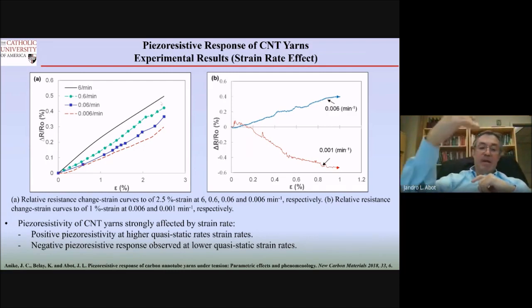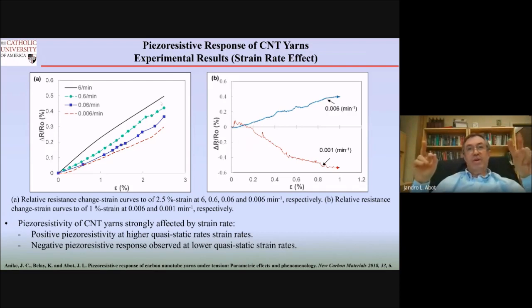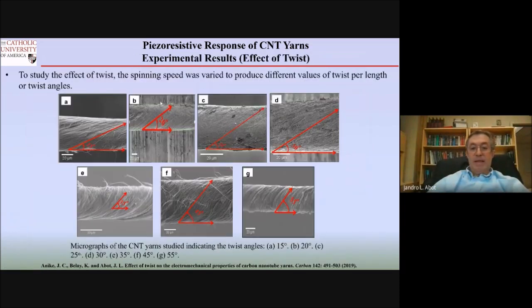If you increase the rate at which you apply the load, the material becomes stiffer. That's what we call the strain rate dependence. In the case of nanotube fibers, this is not different, in the sense that the piezoresistive response will be dependent on the strain rate. Maybe a small thing for me to mention, but the point is that the fiber is dependent on the speed at which you test it. And there are so many other parameters like this that play a role.